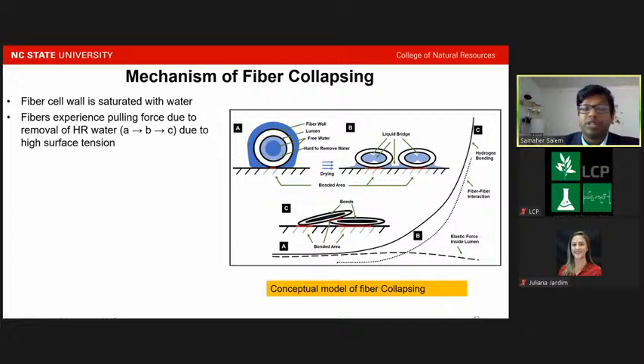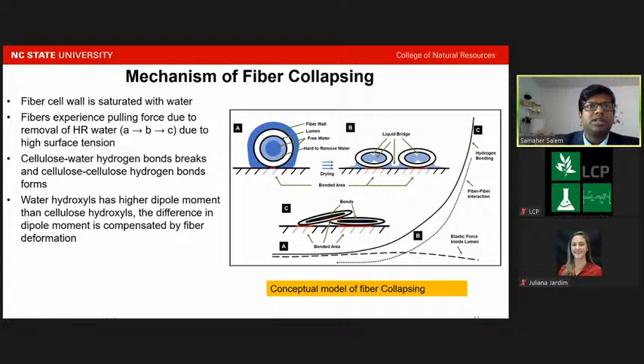What happens when we try to dry the cellulose and remove the water? We could say that the fiber wall in figure A is saturated with water. And as we try to remove the water, the fiber experiences a pulling force due to removal of water, due to the presence of very, very high surface tension. The cellulose-water hydrogen bond breaks and the cellulose-cellulose hydrogen bonds form.